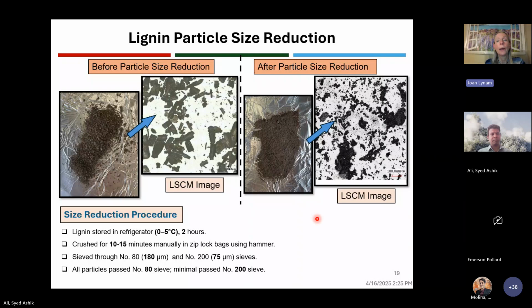And we also had to do a particle size reduction. So we took the stuff right from the reactor after we filtered it. We stored it in the refrigerator for 2 hours. Then we just put it in a plastic bag and hammered it. And doing that, we were able to make it all pass a number 80 sieve.